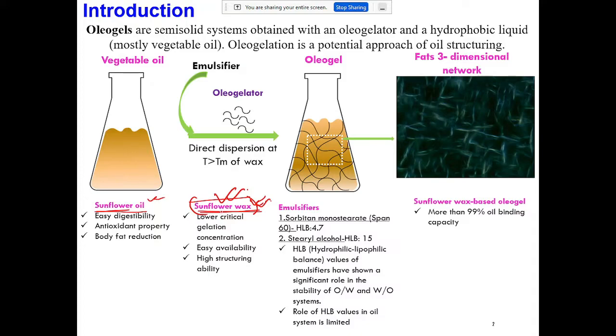So what we did is that to the sunflower oil, we added sunflower wax in different concentrations, and then we heated it, because sunflower wax is solid at room temperature. And when we started increasing the solid content of the sunflower wax, we found that at 5% composition, the sunflower wax was able to induce gelation of the sunflower oil, so that we have a sunflower oil, sunflower wax oleogel.